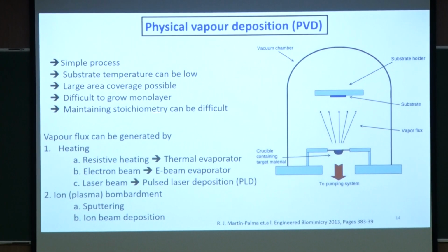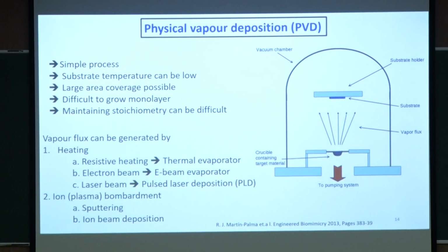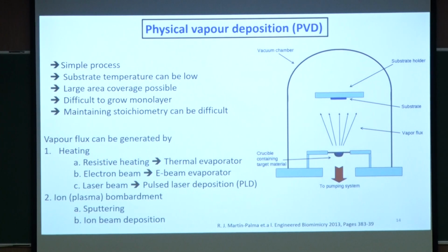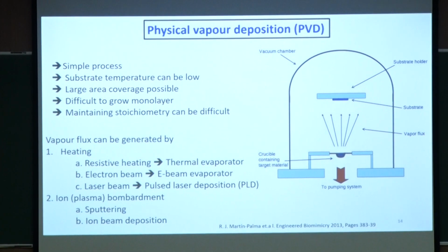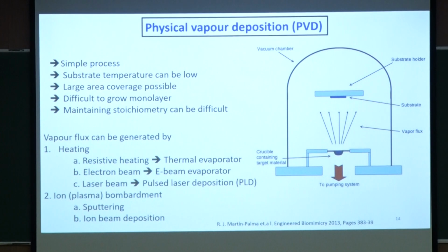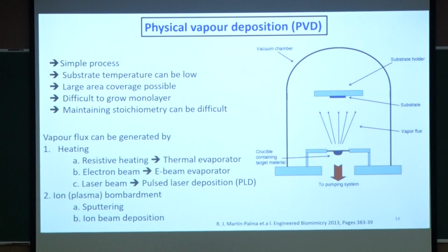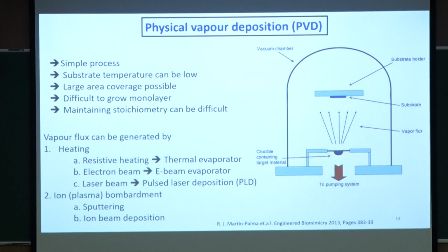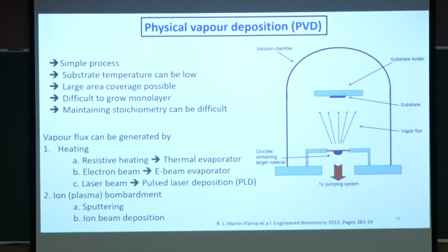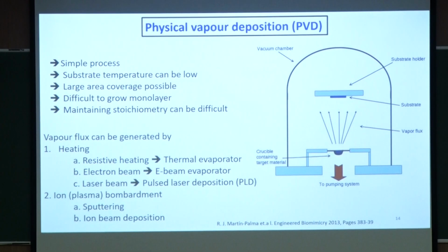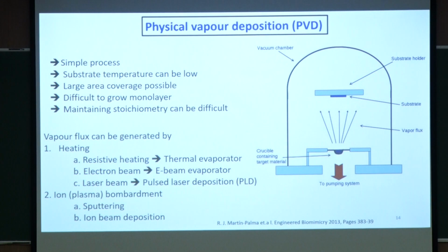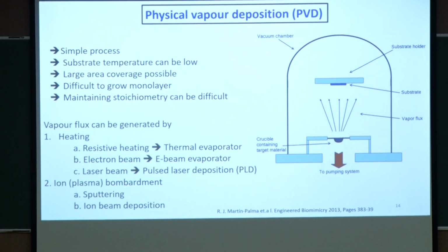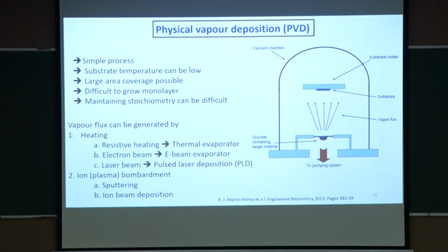But the problem is that it's very difficult to grow monolayer. If you are happy with few layer, then it's okay. People are trying to grow monolayer, but it is not very reproducible. Also, maintaining stoichiometry is sometimes very difficult. You may be depositing MoS2, thinking that you grew MoS2, but it may be MoSx, where x is not 2, close to 2, maybe plus or minus something.